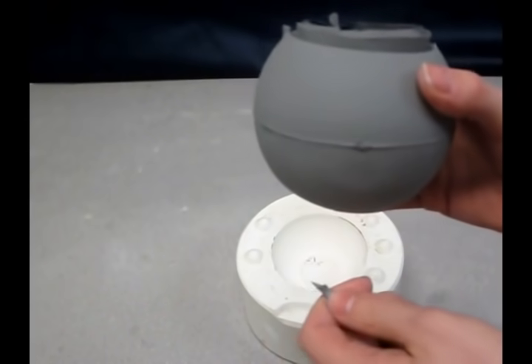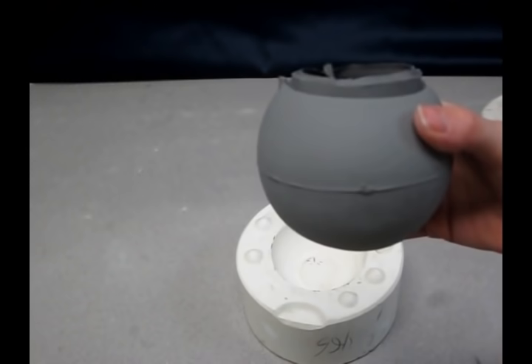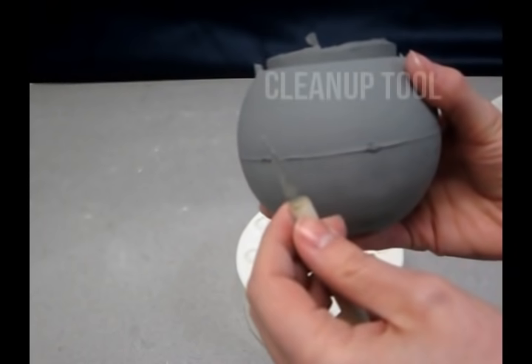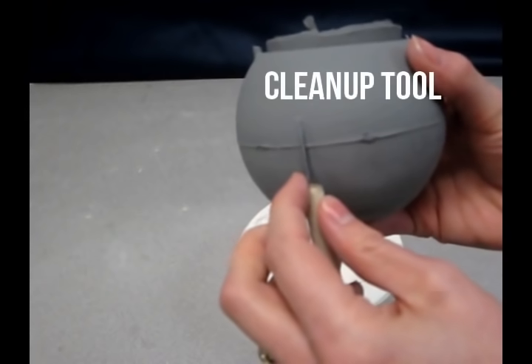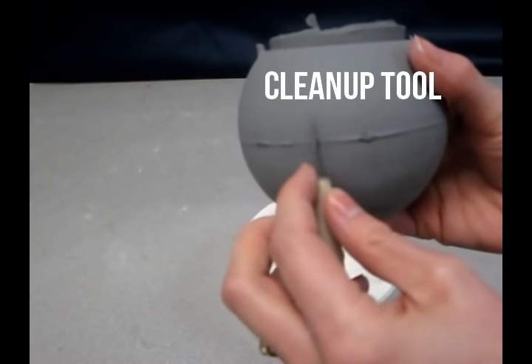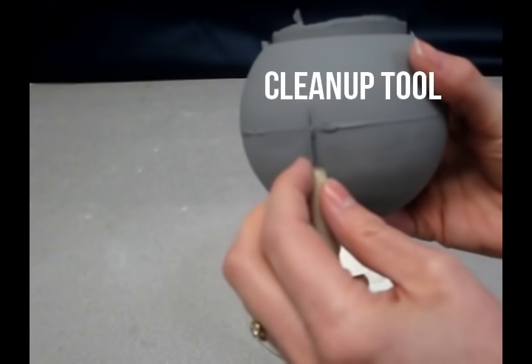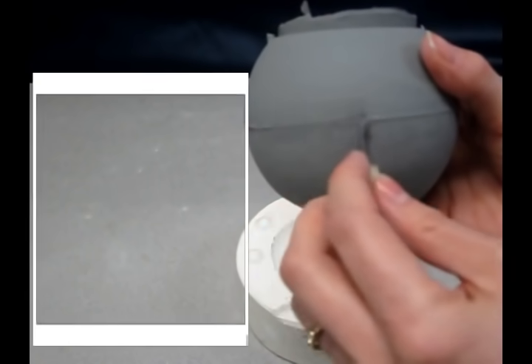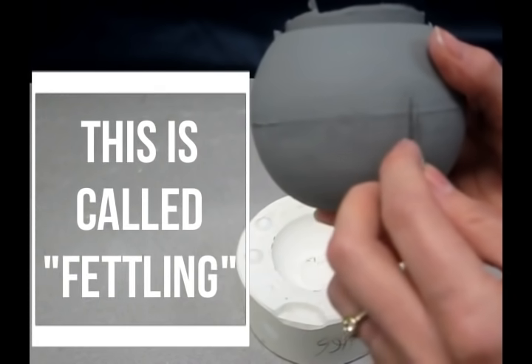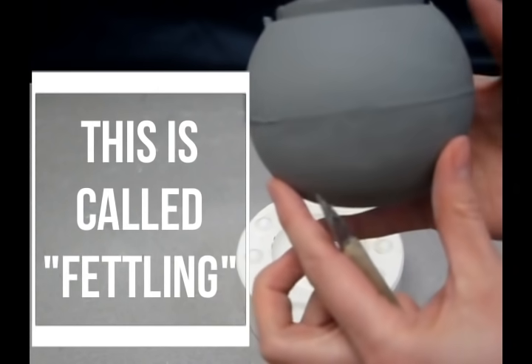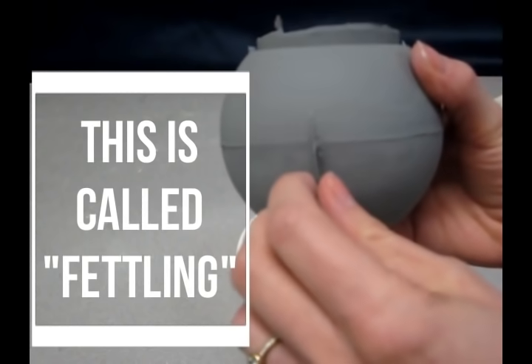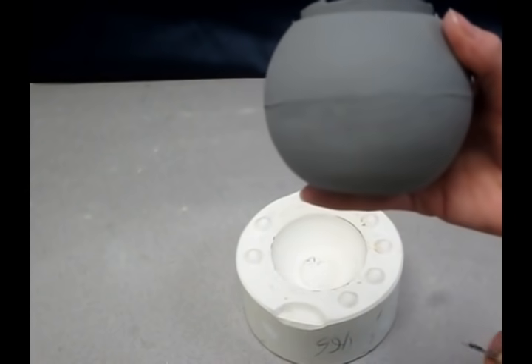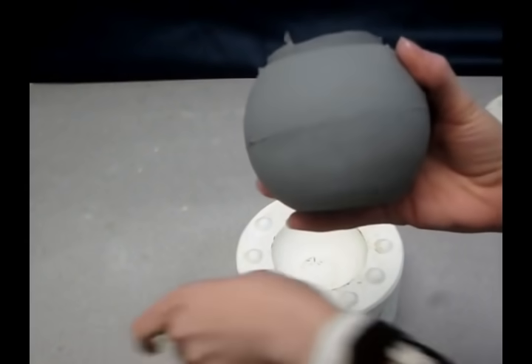So either now while the clay is soft or I can wait until it's more leather hard. I recommend waiting until it's more of a leather hard. You can take a cleanup tool and very lightly trim and shave some of that away. If you wait until the clay is leather hard and not as soft as I'm working with right now, you're less likely to leave accidental scratches or marks. My clay is still very soft. I just wanted to demonstrate.